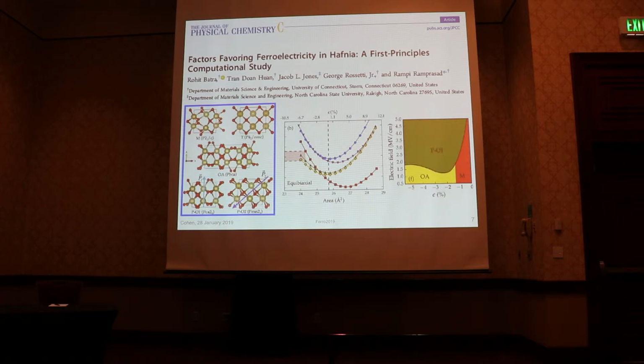And this is the problem that's really hit all of the theorists over the head, because you would like a nice, simple story that you just epitaxially strain the system and it automatically becomes polar. But in all of the calculations, it always comes out that a nonpolar structure is more stable than the polar one. So even though, here's the monoclinic structure, and then if you put in a compressive strain, this orthorhombic structure becomes more stable, so that's nice. Except the one that's observed experimentally is the black curve. And instead, in theory, one always gets the nonpolar one to come out instead.